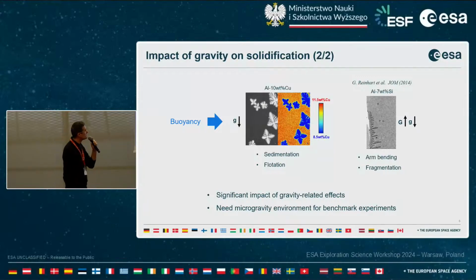Another one will be the occurrence of fragmentation. You can see here a nice aluminum silicon alloy with the columnar dendrite. You can see the secondary arms growing further and further, and after a while, well, what should happen? When they are heavy enough, they will tend to bend and fall down and induce fragmentation, which is something that we do not want because it can be at the origin of defects in the final ingot. So since we have a significant impact of gravity-related effects, we have a need for a microgravity environment to carry out benchmark experiments.